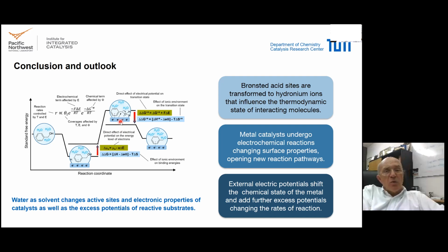But I also wanted to convince you that water as a solvent, and many of the protic solvents, really change active sites, they change the electronic properties of the catalysts, and they change excess potentials of their reactive substances that are being converted. This is not an additive process. This is really a chemical reaction that takes place.